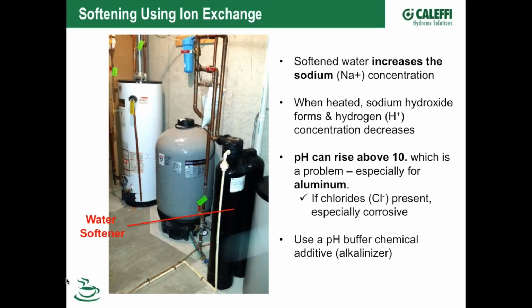All right, that's especially problematic, especially if your water in your system has chlorides. Now we're finding more and more well water tested to have what? Chlorides. Because quite frankly, when you do the backwash on your water softener, you're basically dumping chlorides out to perhaps your septic system, right? And that can leach down into your aquifer. So bottom line is, be careful with water softening.